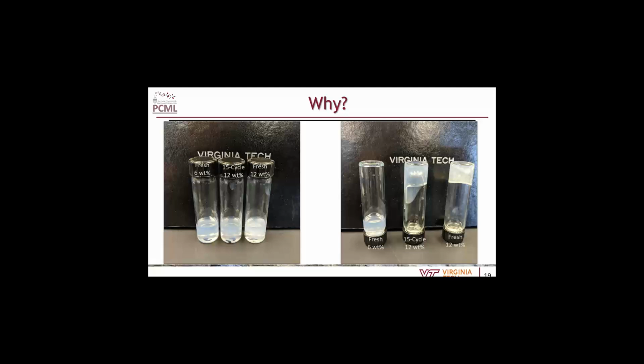The sample that has been subjected to 15 tests starts to flow more like honey when you flip it over. So it's not quite the same as a 6 weight percent, not quite the same as the 12 weight percent. So we really wanted to know what was happening.